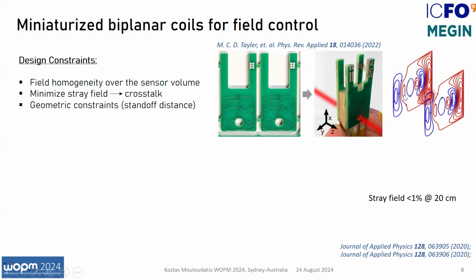And these current loops are designed having in mind some design constraints. Some of them are related to the magnetic field, but some others are geometric constraints. For example, we want as high field homogeneity as possible at the place where the vapor cell is placed, at the sensor volume, but also we need minimal stray field to avoid crosstalk between different sensors. But also there are geometric constraints, like this hole, for example, should be as close as possible to the edge of the PCB such that the standoff distance from the scalp is minimized.